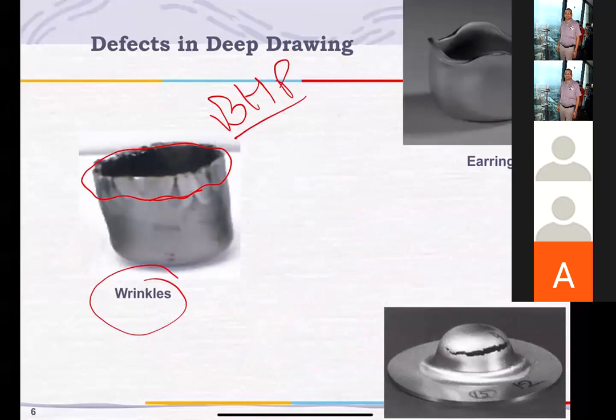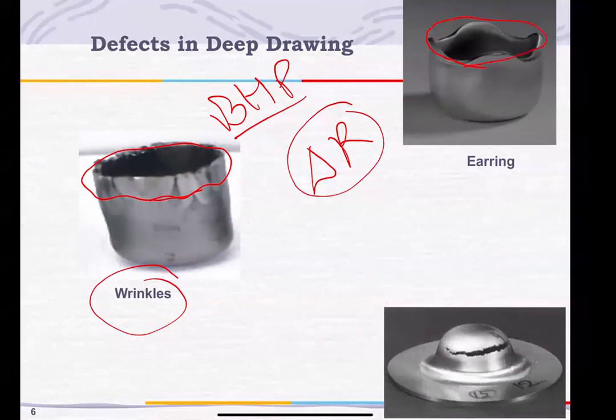Now, there is earing. Professor Mishra was also speaking about earing. The earing we cannot avoid because it appears due to the delta R value of anisotropy. Delta R is (R0 minus twice R45 plus R90) divided by 2. And when there is a larger value of delta R, this ear height will be more. This ear height will be more when the delta R value is high.